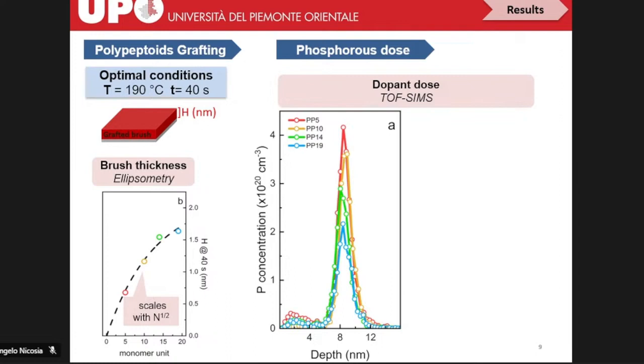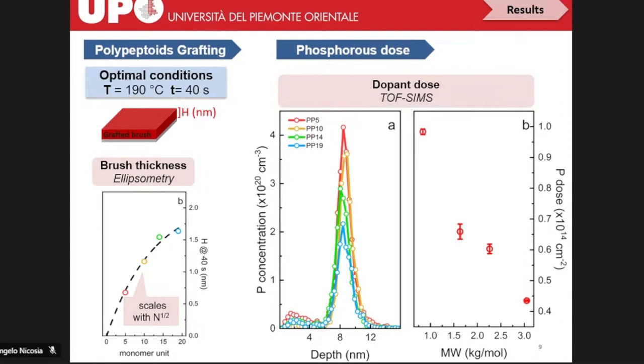If we integrate these profiles, we can calculate the phosphorus dose. And from the graph, when we plot the phosphorus dose as a function of the molecular weight, we found an inverse relation. But the most interesting thing is that if we compare these experimental results with the expected grafting density of the polymer calculated from the radius of gyration of the polymer, we found a perfect match of the values.